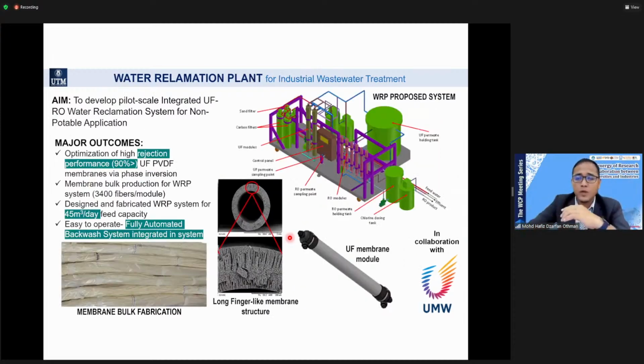This project is almost finished, where we develop a water reclamation system using a hollow fiber polymeric membrane as well. We developed by our own an ultrafiltration membrane using polyvinylidene fluoride, and we are able to reject more than 90%. In fact, this is much higher than the commercialized one. We compared with some commercial membranes, and we achieve a few percent higher rejection. The capacity of this plant is 45 cubic meters per day and it can reclaim water from industrial wastewater.